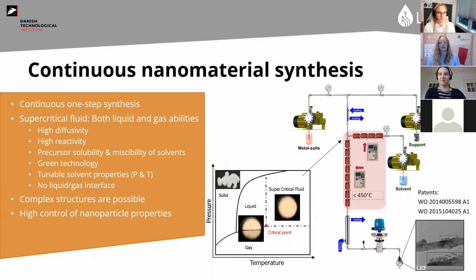And since we have such a low volume in the area where the supercritical fluid hits the cold reactants, we also have very narrow size distributions, which is very good for catalytic systems. And it's also really good to produce particles on a support because it's going to be very well distributed and has a very nice small particle size distribution again. So that's where it's better than the impregnation method, for example.